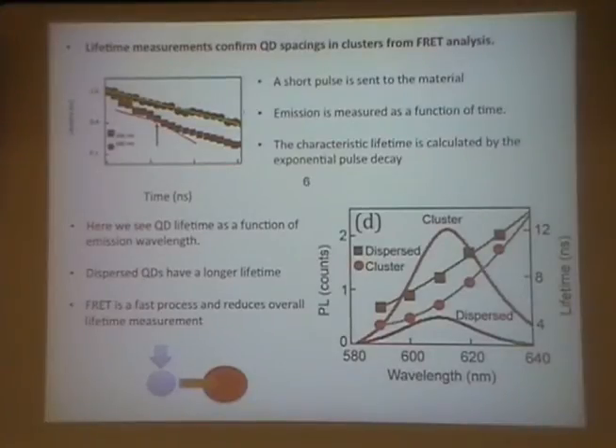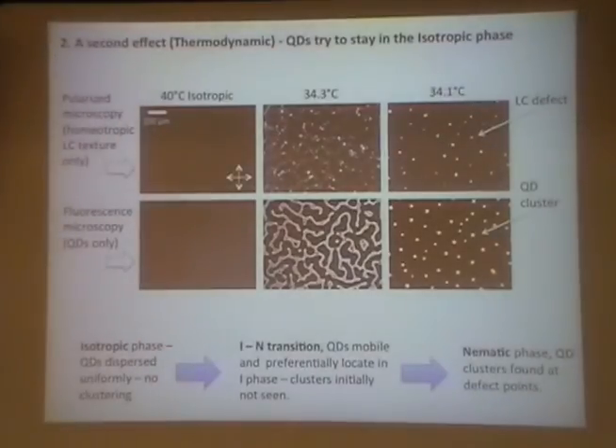So now I have to show a few more results, and then that will be the end, just a couple more minutes. I'm going to skip this because I'll talk more about that in the next talk. I just want to show these results. So I talked about the elastic effect and the thermodynamic effect. The elastic effect was the clustering. Particles, when they're in the nematic phase, just group together and reduce the elastic cost. But another thing that we see when we go through the transition, which actually might be even more significant in terms of making a material, is that they just do not want to be in the nematic phase at all